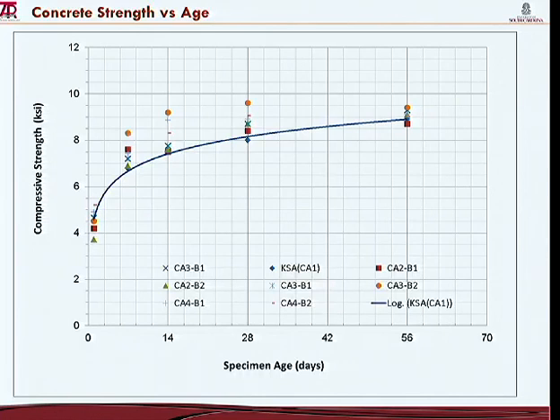So this is what we got from this first trial where we mixed the different batches. This is the compressive strength versus specimen age. And we can see that the limestone, which is the standard, is pretty much the lowest strength of all, especially at early times. At 56 days, the strength is about the same for all batches, so we didn't lose strength there. And also notice that these data are for multiple batches of the same aggregate, just to test the repeatability.